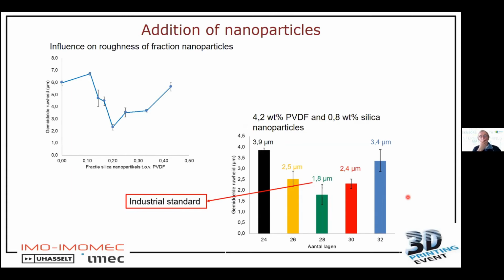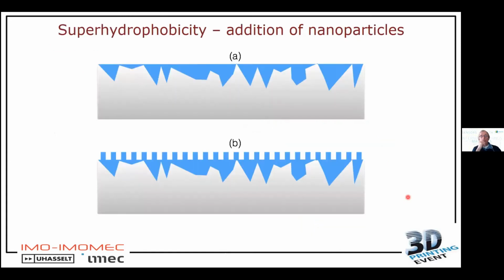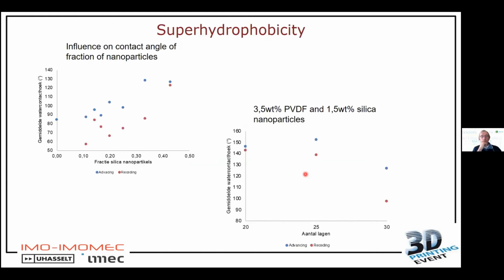But there is another advantage of using nanoparticles. If you look at a surface that is very, very smooth, then your wetting is completely different than when you have a structure-like substrate, which still has a bit of roughness. And that's what we try to achieve by using nanoparticles, because if we spray these nanoparticles in this ink, you still have a specific roughness below 2 micrometers, but it's some kind of periodic, and this can help in achieving this easy to clean property.